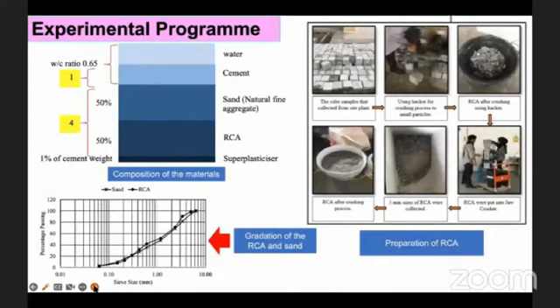This is the composition of the material, which consists of water, cement, natural fine aggregate, recycled concrete aggregate, and superplasticizer. In this case, we use a water cement ratio of about 0.65. The mixture of the concrete was based on a ratio of 1:4, 1 for cement and 4 for aggregate. The natural fine aggregate was 50% and recycled aggregate about 50%, and then we added 1% of superplasticizer based on cement weight.